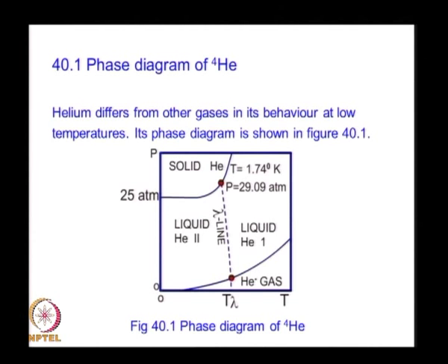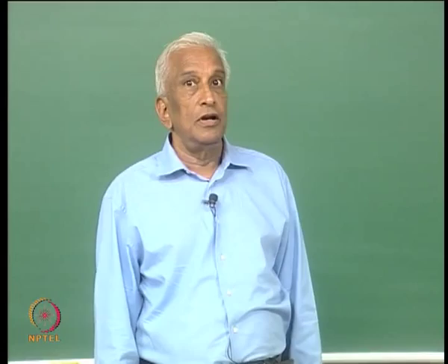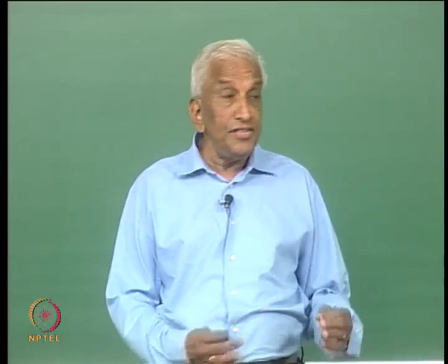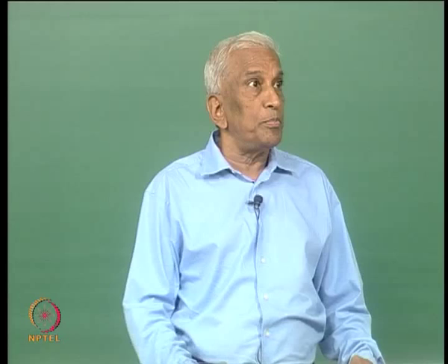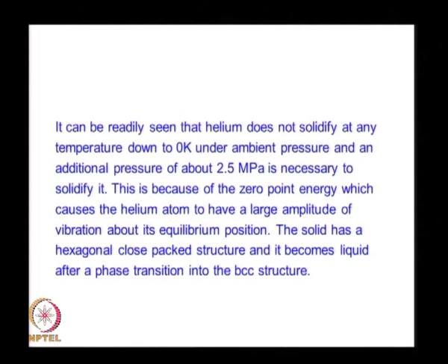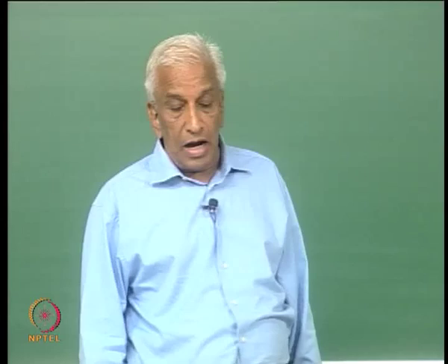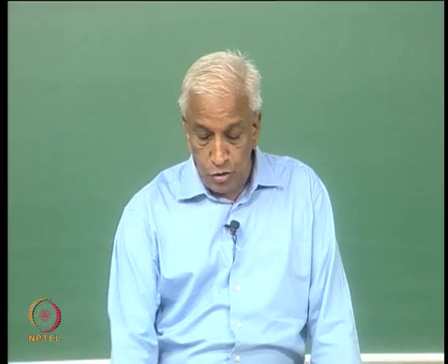One can readily see that helium does not solidify at any temperature down to absolute zero under ambient pressure. An additional pressure of about 2.5 megapascals, which is 25 atmospheres, is necessary to solidify it. This is because of the zero point energy, which causes the helium atom to have a large amplitude of vibration about its equilibrium position in the solid. The solid has a hexagonal close packed structure, and it becomes liquid after a phase transition from the HCP into the BCC or body centered cubic structure.